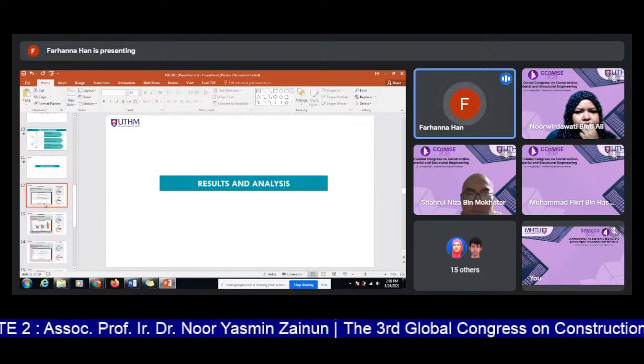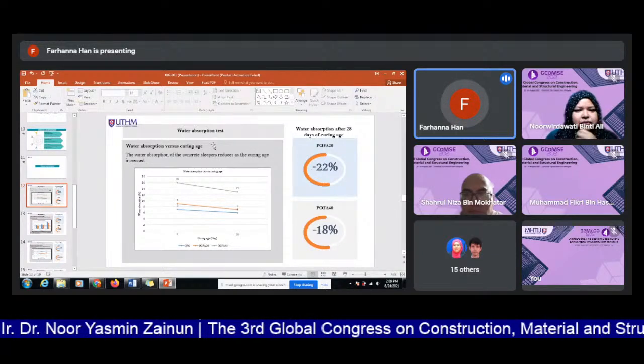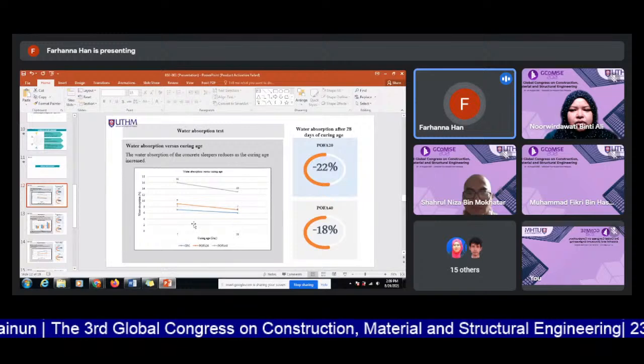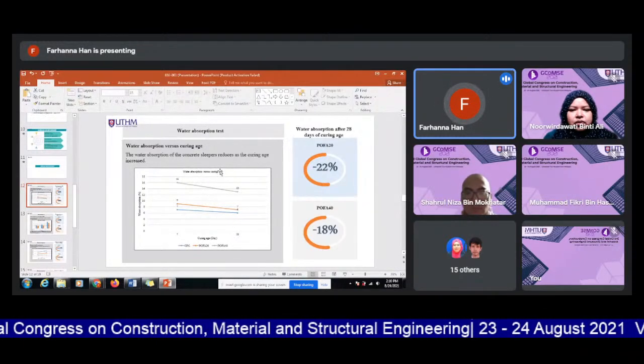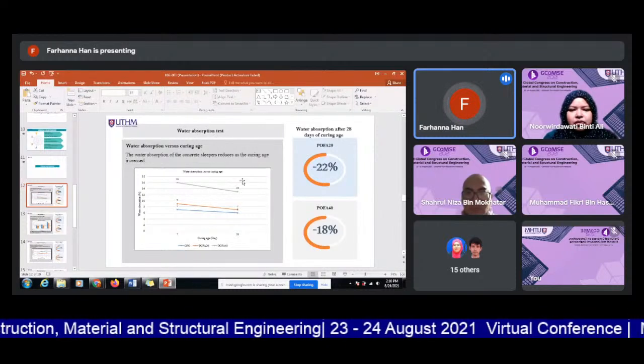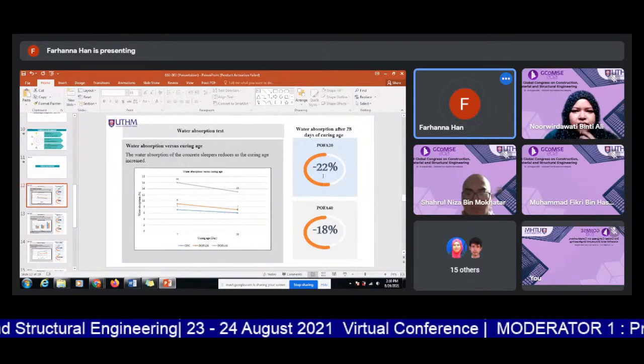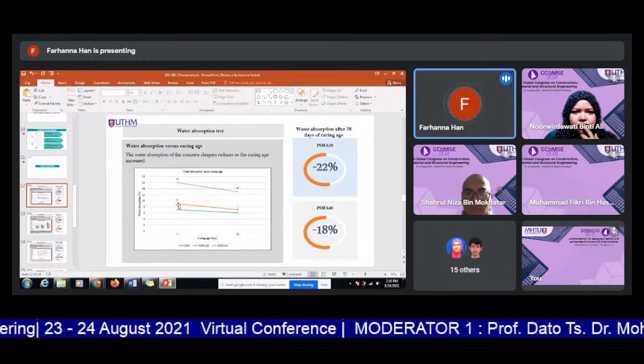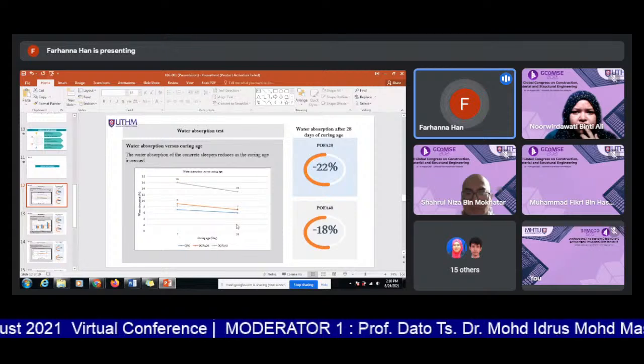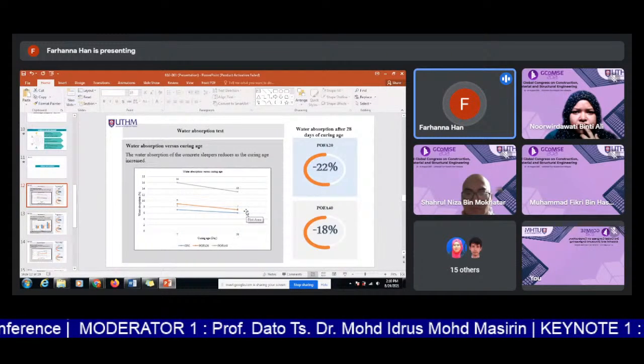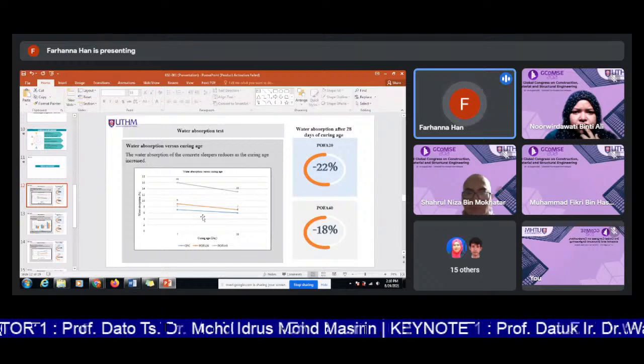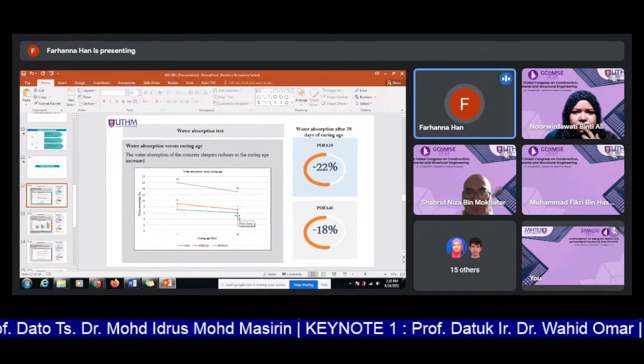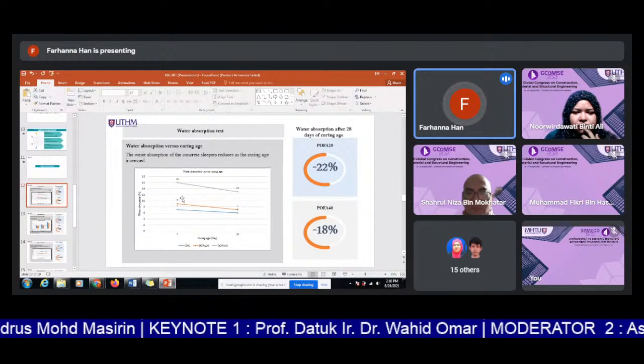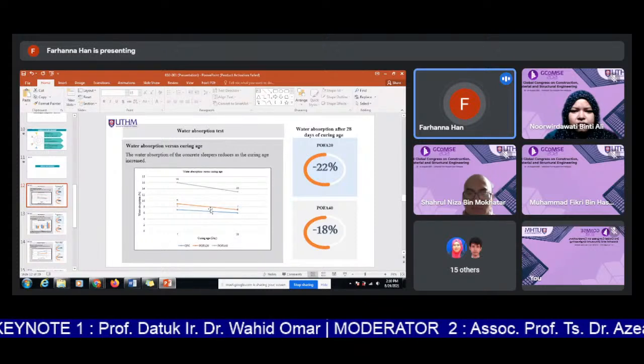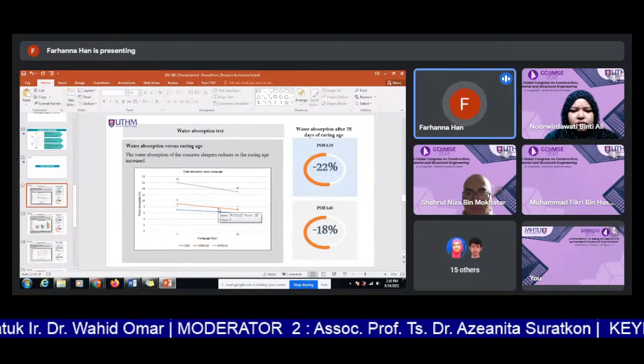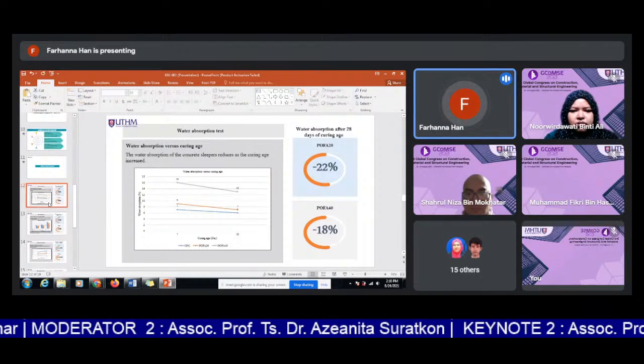So this is my result and analysis. This is the result for the water absorption test versus the curing age at 7 and 28 days. From the result, we can see that as the curing age increases, the water absorption of the concrete sample reduces. For POFA 20, the water absorption reduced by 22% from 7 to 28 days of curing age. And for POFA 40, the water absorption reduced by 18% from 7 to 28 days. So this indicates that the pozzolanic reaction of the sample occurs. It improves the microstructure of the sample along the curing age, fills the voids and reduces the porosity of the concrete.